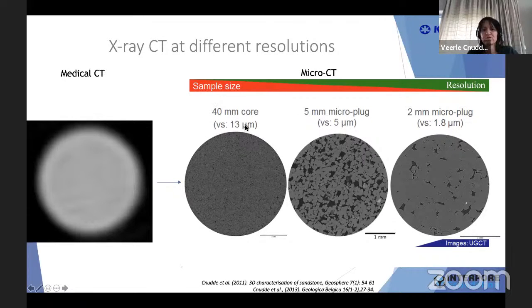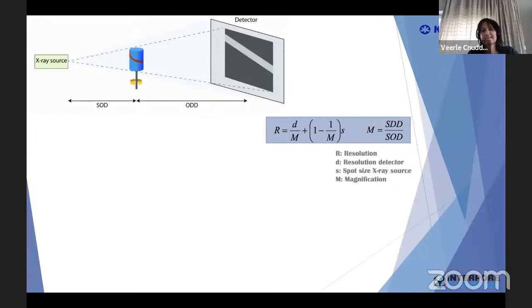Here you have an overview, and you see immediately that depending on the diameter of your material, we have a different voxel size. With a sample size of 40 millimeters diameter, the voxel size is 13 micron. With a micro plug of 5 millimeters diameter, voxel size is 5 micron. And with a 2 millimeter micro plug, voxel size is 1.8 micrometer. So you see there is a link between sample size and resolution, because resolution is depending on the sample size.